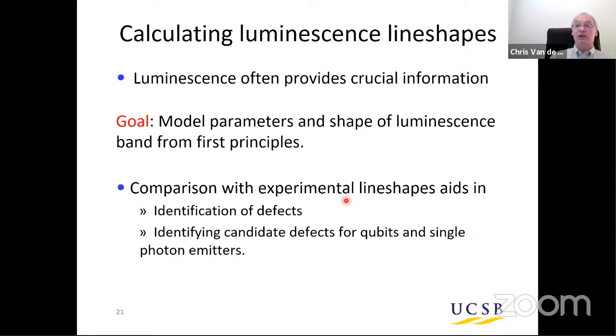As I mentioned, in the case of yellow luminescence, the emission is actually broad, and that can happen because you can have transitions not just for one particular atomic configuration, but at a finite temperature or even at zero temperature. Because of zero-point motion, the atoms are always moving, and that's going to lead to a broadening of the line shape, which we can actually also explicitly model from first principles.